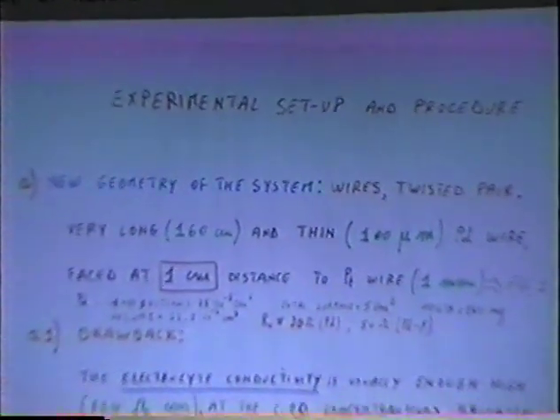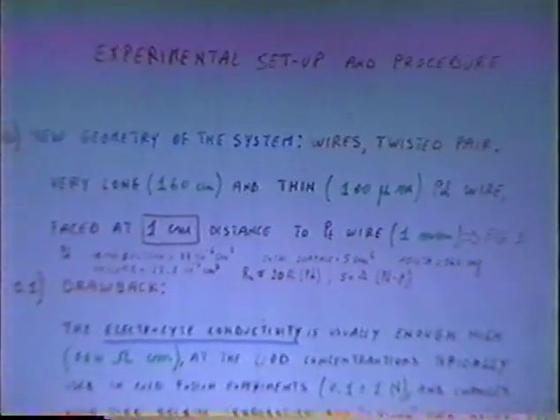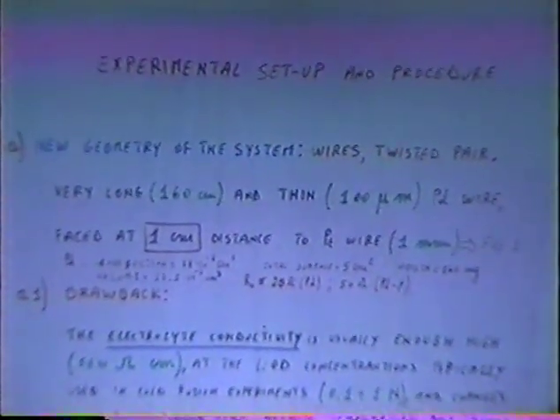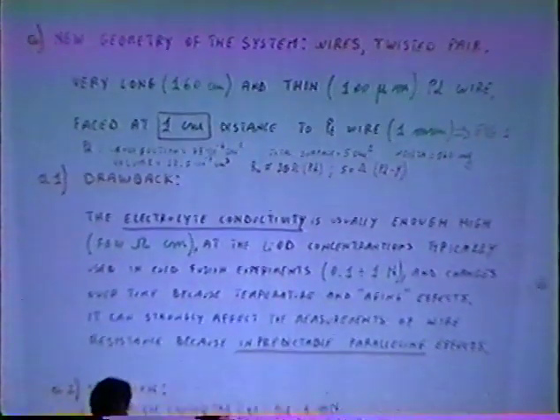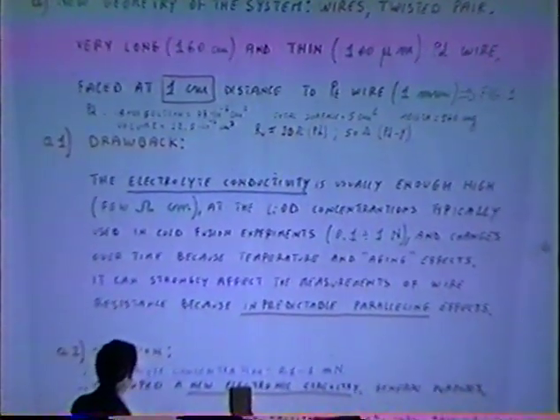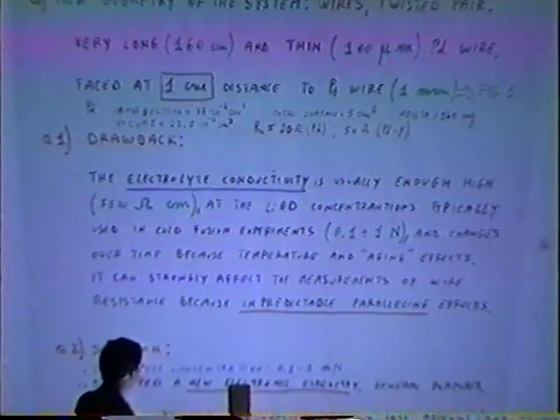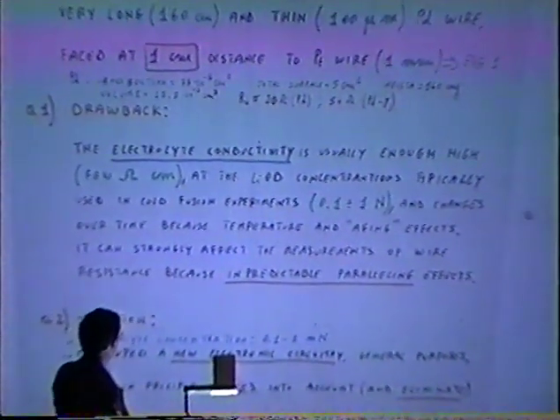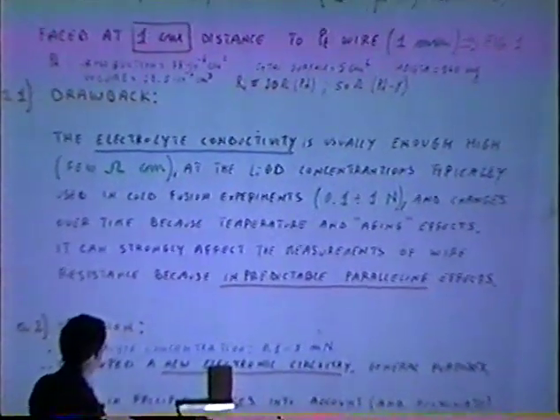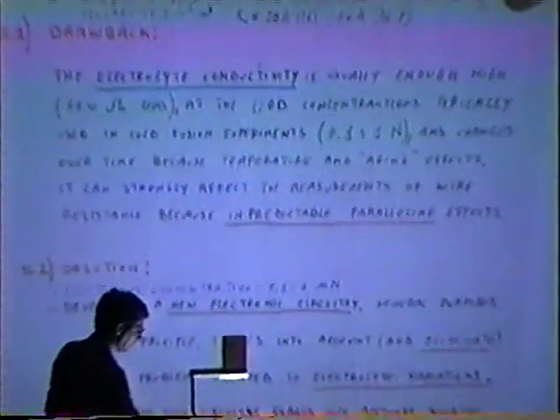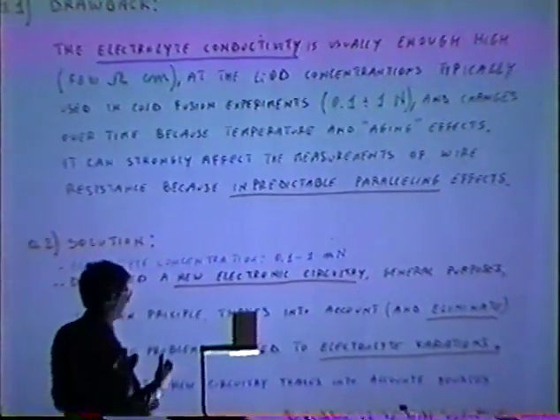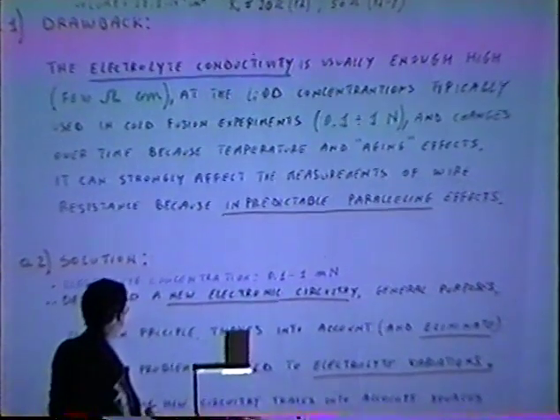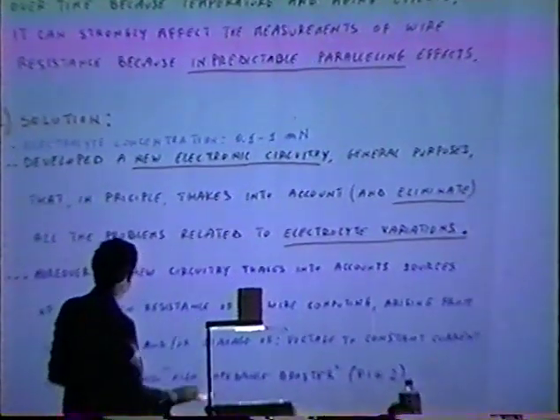The experiment setup is very new. We used wires, twisted pair, very long, about 1.6 meters, and quite thin, only 100 micron. Distance is about 1 centimeter. Just to have an idea, the total resistance is 20 ohm, the wire weighs 160 milligram. The drawback of this configuration is that the electrolyte makes a big parallel effect, so it's very difficult to measure the resistance, but we overcome this problem.